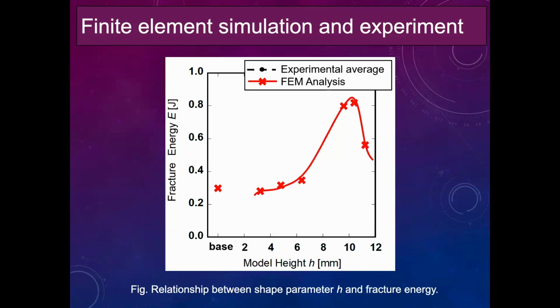This is the relationship between the shape parameter H of the sickle joint geometry and fracture energy. Here, the fracture energy was defined as the area under the load displacement curve. This red line shows the FEM result. From this result, the fracture energy increases with the shape parameter H. The maximum value of the fracture energy was taken at H equal to 10 millimeter here. After that, the fracture energy decreases, as shown here. This is the FEM result.